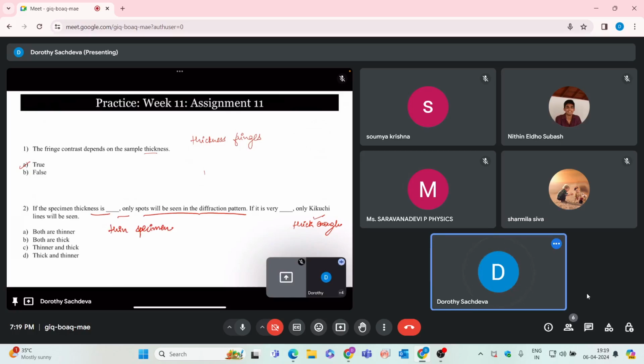So if the specimen thickness is thin, only spots will be seen in the diffraction pattern. If it is very thick, only Kikuchi lines will be seen. So there should be some optimum thickness of your specimen so that you can see the Kikuchi lines as well as your diffracted spots. Kikuchi lines will be used for tilting the specimen and diffraction patterns will be used for the further analysis of your specimen. So the answer for this case will be option C, thinner and thicker.